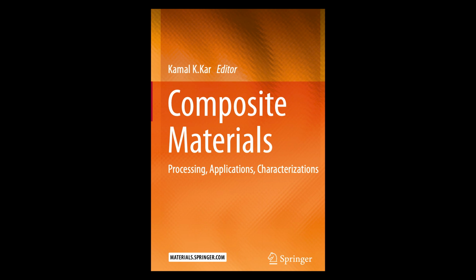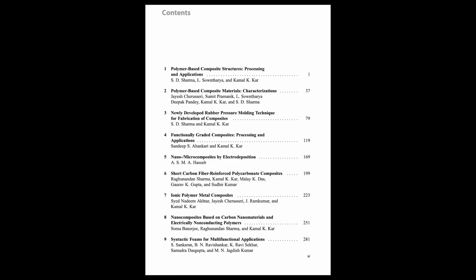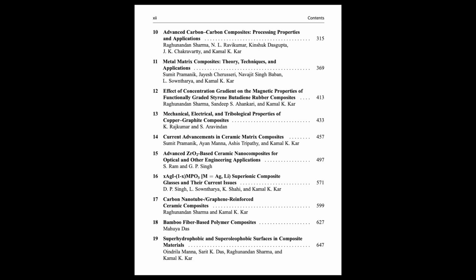Applications: high-wear parts like bearings and seals, but also advanced aerospace turbine engine components, thermal protection systems, where metals simply can't survive. And just touching on a few others quickly, ZrO2 nanocomposites, superionic glasses, even bamboo fibers. The field is huge. It really is. Zirconia nanocomposites show how nanoscale control of structure and additives can tailor ceramic properties, magnetic, electrical, optical. Superionic glasses are pushing boundaries for solid-state batteries. And using natural fibers like bamboo shows a move towards sustainable, high-performance composites, too.